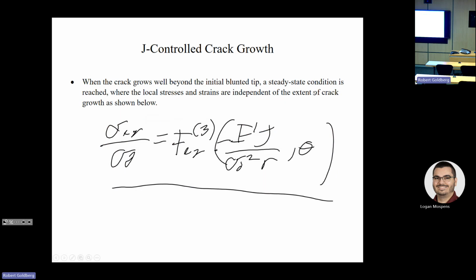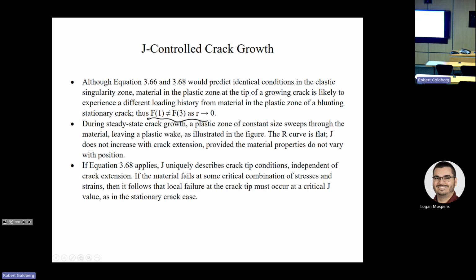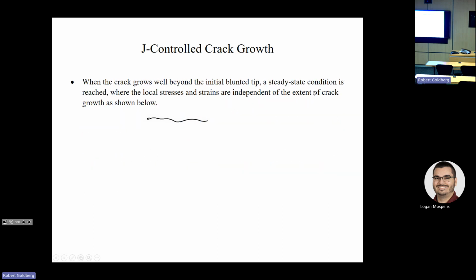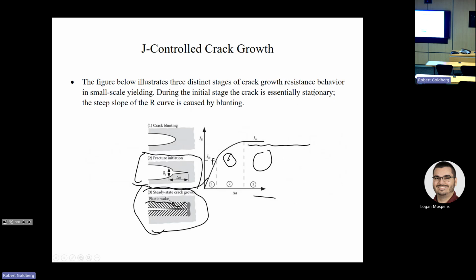So if this equation applies for the zone 3 response, J uniquely describes the crack tip conditions independent of crack extension. And if the material fails at some critical combination of stresses and strains, then the local failure at the crack tip must occur at a critical J value, just as in the stationary crack case. And because our R curve is flat here, this critical J value remains constant with crack growth. And if we had a rising or falling R curve, it would be due to the fact that the local material properties are varying with position.